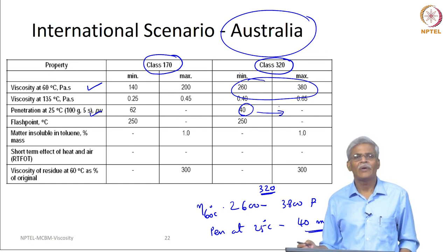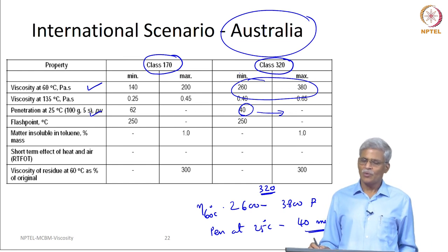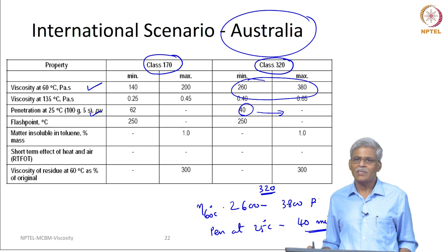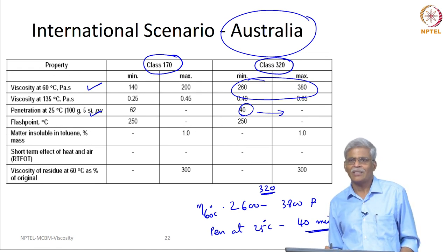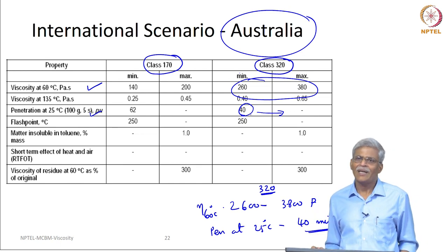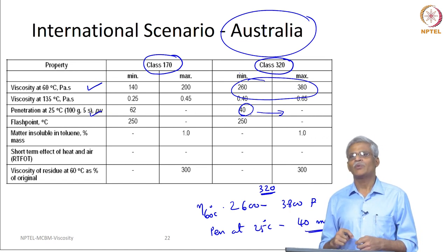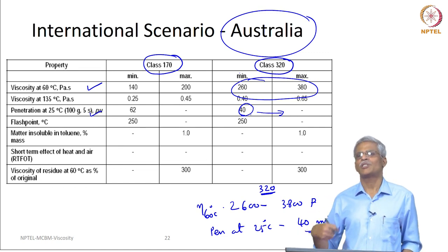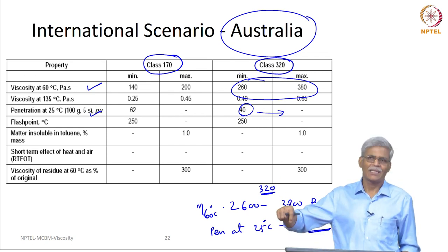It will be very nice if you could have a penetration of 40 for such a material, because 2600 to 3800 is a very good bitumen at 60 degree centigrade, and if you could have a penetration of 40 at 25 degree centigrade, you will also be able to handle the fatigue damage that can happen. Please do not try to relate the penetration with fatigue directly. What I really wanted to say is a low penetration means a stiff material, and a stiff material is likely to have more tendencies for fatigue damage at that temperature.